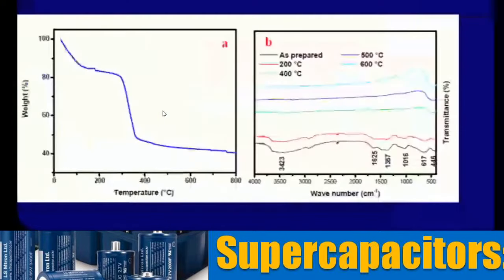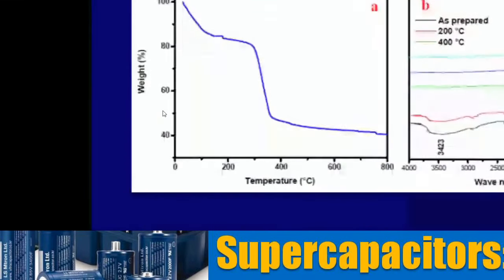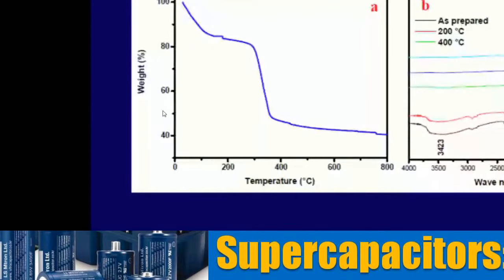The first and foremost thing, you may ask me why you want to do it. The graph you see on the left side is known as thermogravimetry. When the material is heated linearly from room temperature to 800 degrees, what happens to the mass of the material? You will see that the mass decreases to about 85% at 100 degrees. Around 200 degrees, there is again a 2-3% decrease in mass. And around 350 degrees, there is a sudden drop in the mass.